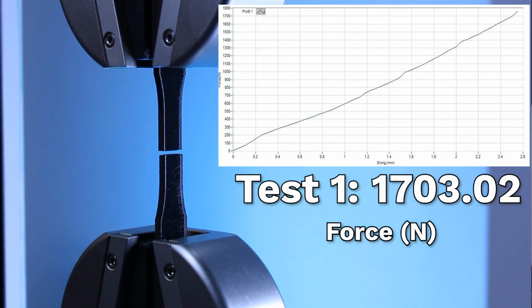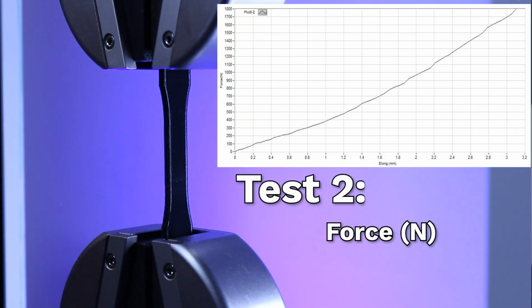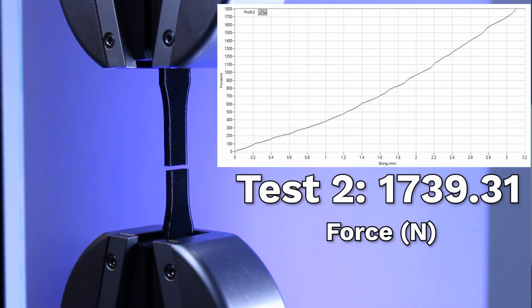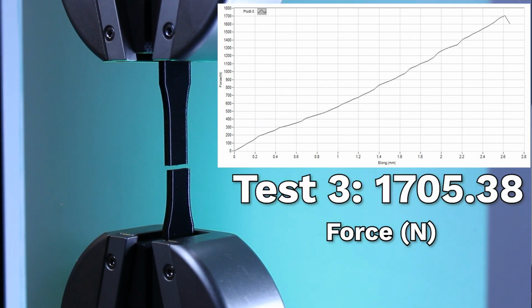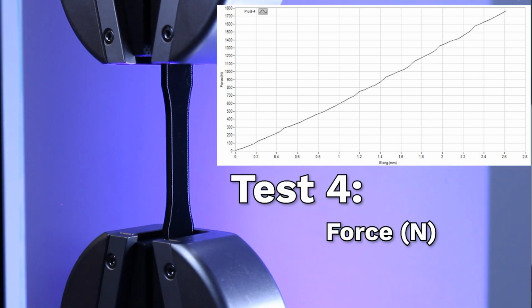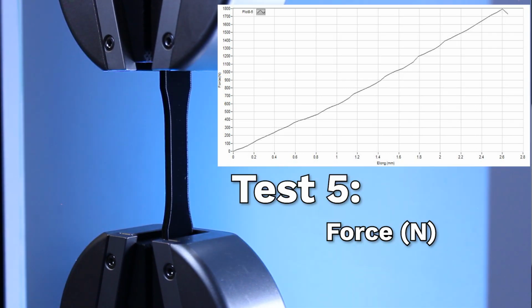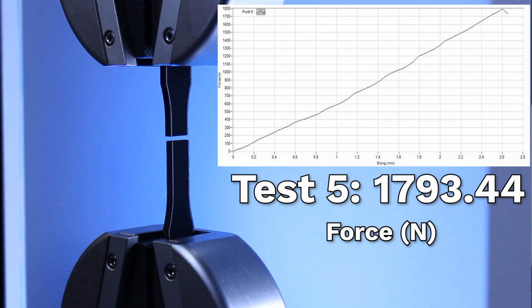We loaded these up onto our machine and they broke off just beautifully. Across all of these tests, we had an average force of about 1700 newtons, which is about 300, 400 pounds, that range, which is 2 full-grown men hanging from a cross-section this big. That's pretty darn impressive in the context of material strength in general, especially when you're looking at a plastic.